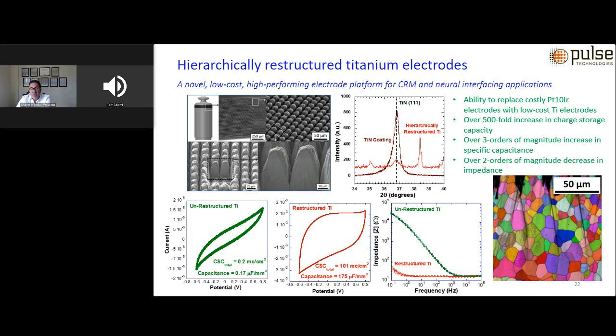For example, in situ synthesis of high surface area titanium nitride, the low cost of the process, because it doesn't require the use of costly platinum iridium electrodes, but instead uses titanium. And unlike PVD-based titanium nitride coatings, it is a maskless process with no batch minimums, as I mentioned. And it creates electrochemically active ultra-high surface area due to the presence of nanostructured titanium nitride that is synthesized in situ during the restructuring process.